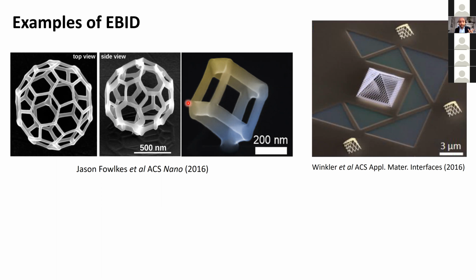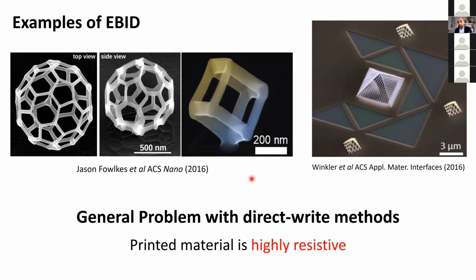for nanostructures, they have the same problem, and that is the fact that all these structures turn out to be highly resistive. And that's not surprising because more than 50% of these structures are actually made of carbon. And the typical mean free path is less than a nanometer, usually only a few angstroms. So this is a very disordered system with a lot of scattering. Nevertheless, there were a lot of efforts to make disordered superconductors with EBID.